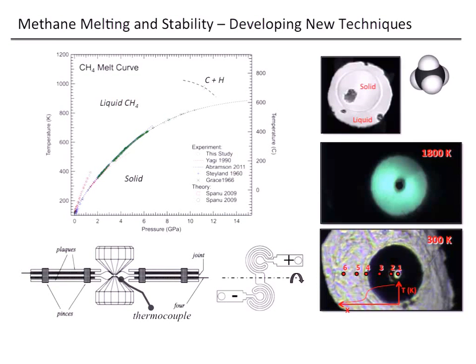It's easy, actually, to do melting experiments if you can heat the sample uniformly. So one of the things I did was work on resistive heating techniques, where we wrap the gasket of our diamond cell with what looks like a little stovetop, and this gets folded over both sides of the gasket so we can heat the circumference of the gasket and consequently heat the sample, which is right between the two diamonds here.